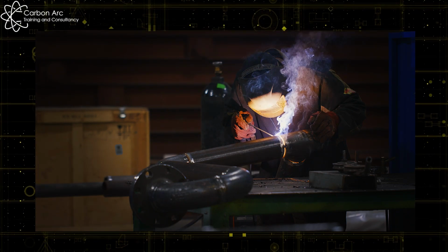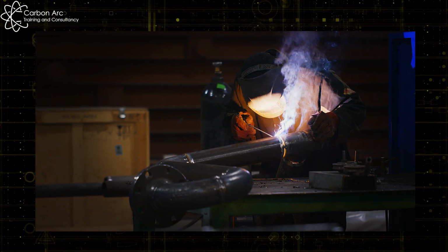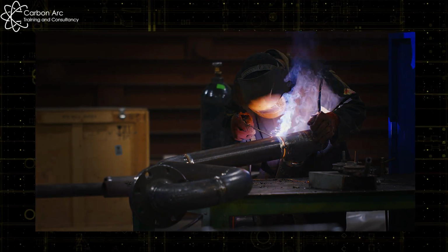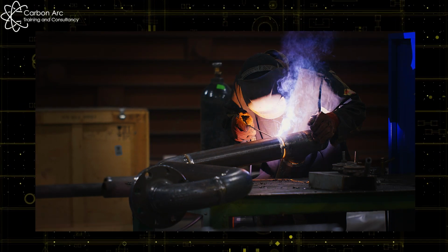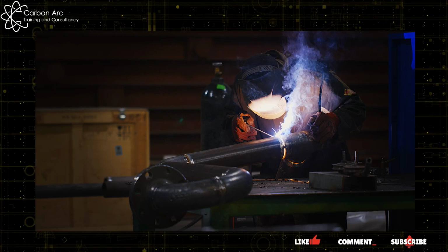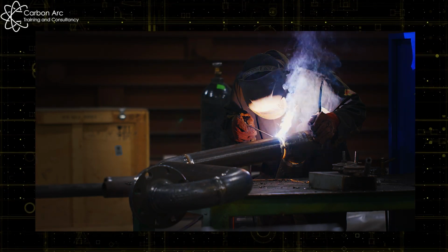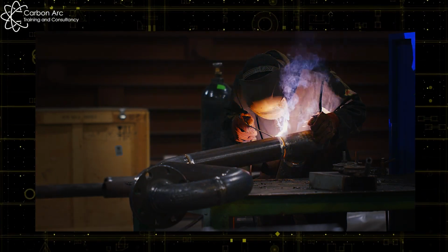We also have a limit on the arc time that we have. As a general number, we're looking at the efficiency of the process being around 30%. So for, say, every 10 minutes of welding, we've only actually got arc on for about 3 minutes. The rest of the time is cleaning, back grinding, setting up our next electrode, and getting ready to start again.